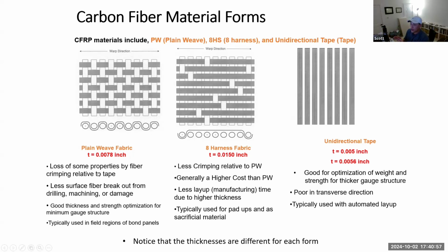What are some of the differences in terms of properties between each of these types of carbon fiber material forms? Plain weave has loss of some properties by fiber crimping relative to tape. That's not good, but that's the downside of a plain weave. It has less surface fiber breakout from drilling, machining, or damage. That's good. It has good thickness and strength optimization for minimum gauge structure, typically used in field regions of bond panels. So in a honeycomb composite bond panel, you'll see plain weave fabric used quite a bit across the bond panel. 8 harness fabric has less crimping relative to plain weave, generally a higher cost than plain weave, and less layup time due to higher thickness. It's typically used for pad ups and as sacrificial material. Unidirectional tape is good for optimization of weight and strength for thicker gauge structure, poor in transverse direction, typically used with automated layup.